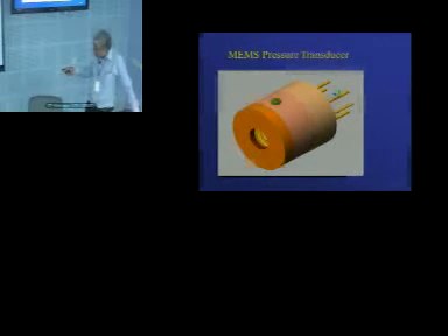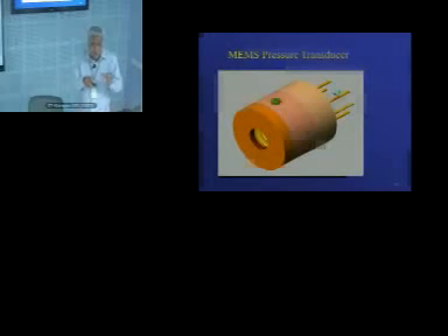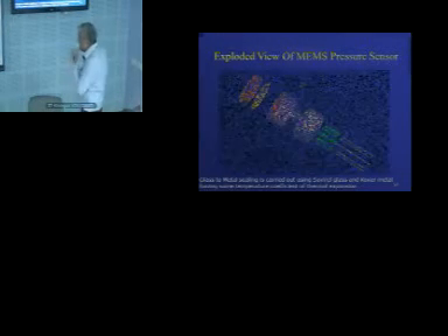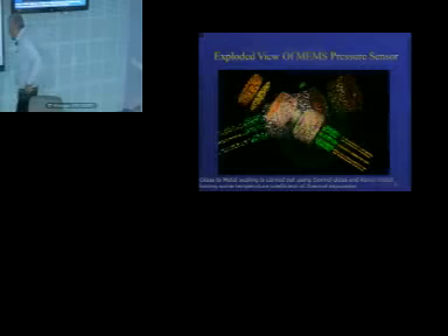So then we have to, like you saw DRIE, deep reactive ion etching, here we go for electron beam welding. The width to depth ratio is very high. So depth you can go very high, like 1 mm, 2 mm, whereas the width is only 0.2, 0.3, 0.4 mm. You can achieve that by electron beam welding. And you see how it is being assembled. You can see here in one of these animations.